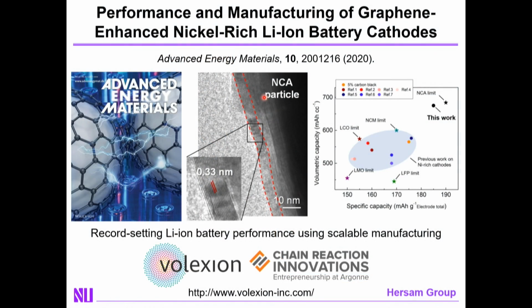If the area of the graphene sheet were similar to the surface area of the particle, then the only way I could get a conformal coating is by wrinkling or crumpling, which would give me gaps. Because our graphene is small compared to the surface area, it goes down flat. So it's like we're tiling or forming a patchwork quilt around the particle, which then begs the question, what about the seams in your quilt?